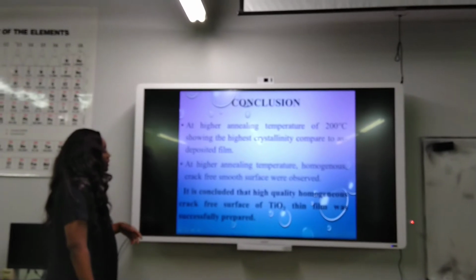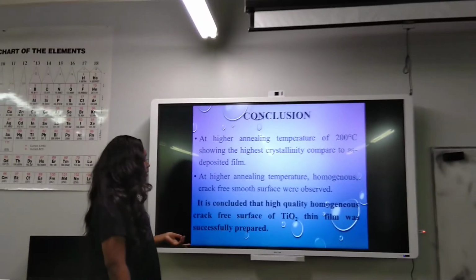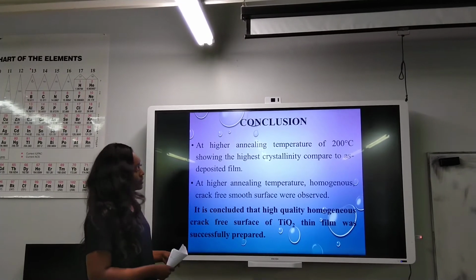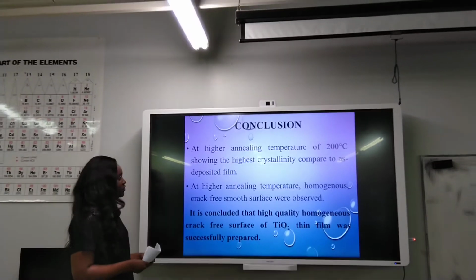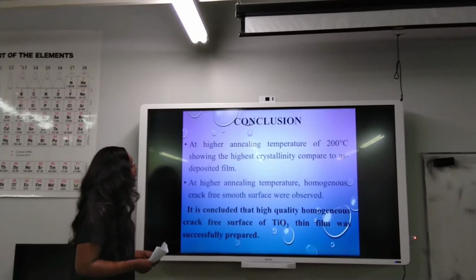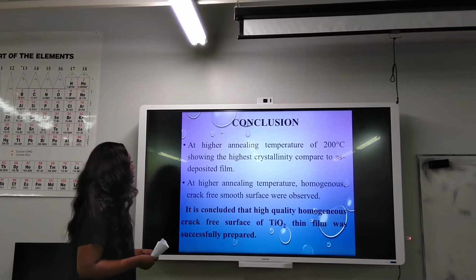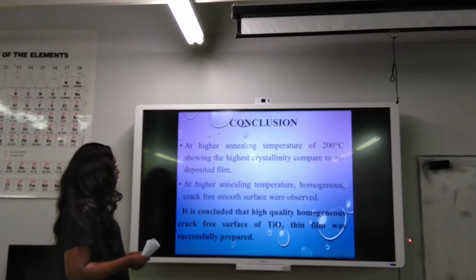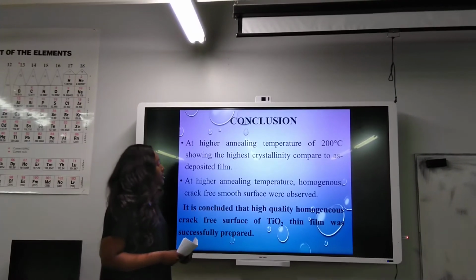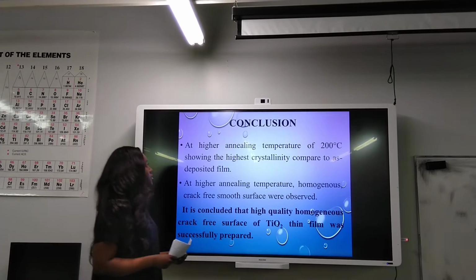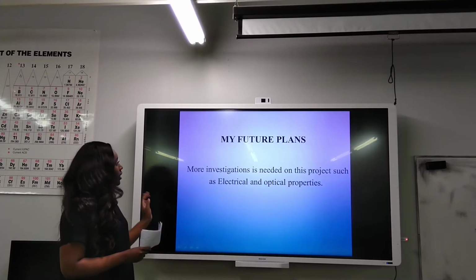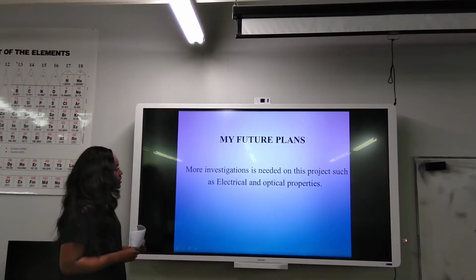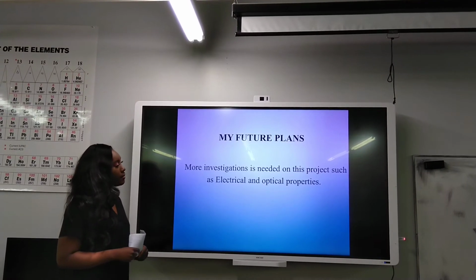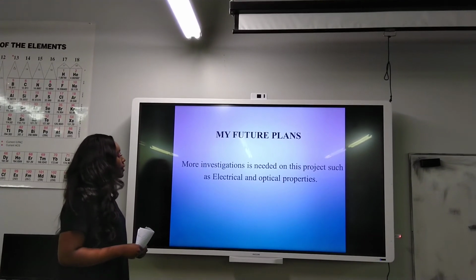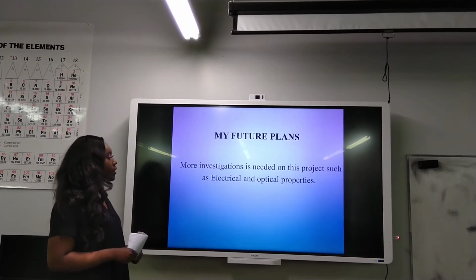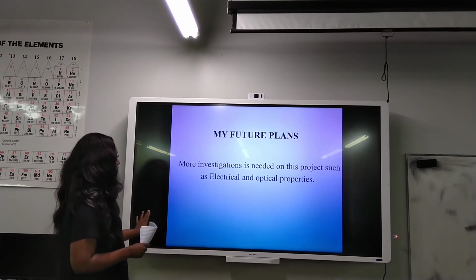So in conclusion, a higher quality, homogeneous, crack-free surface of TiO2 thin film was successfully prepared, and at the higher annealing temperature, 200 degrees Celsius, it showed the highest crystallinity compared to as deposited film. And my future plans are to investigate the research project more, like using the electrical and optical properties.